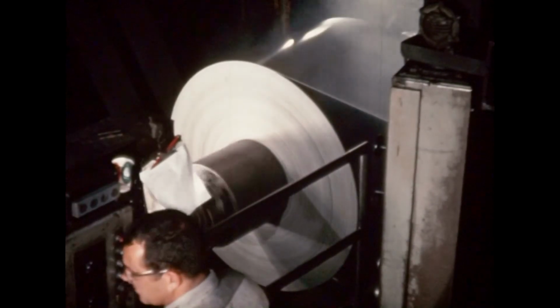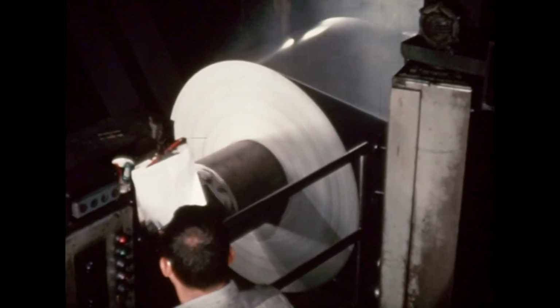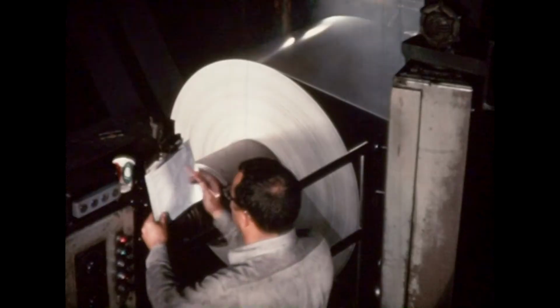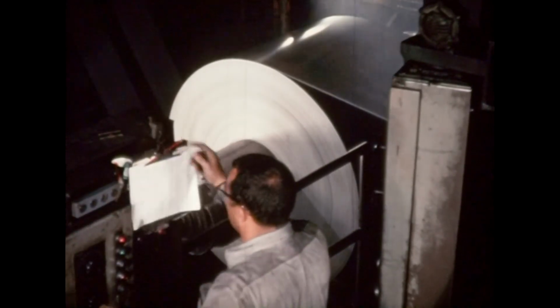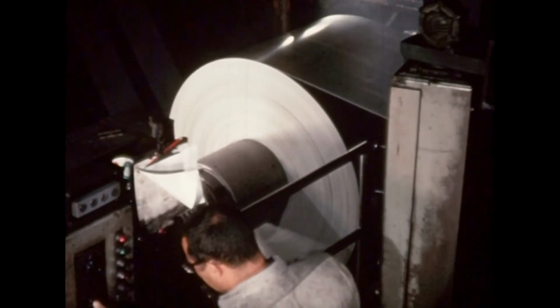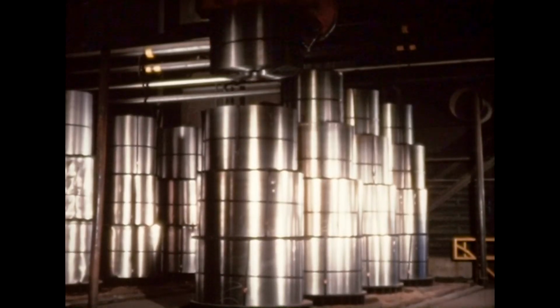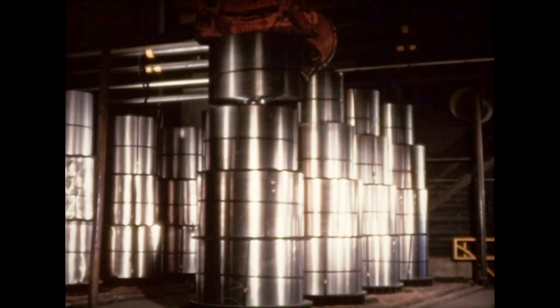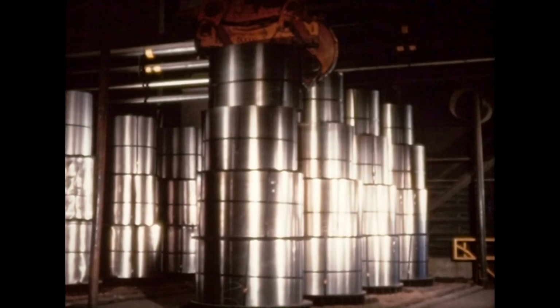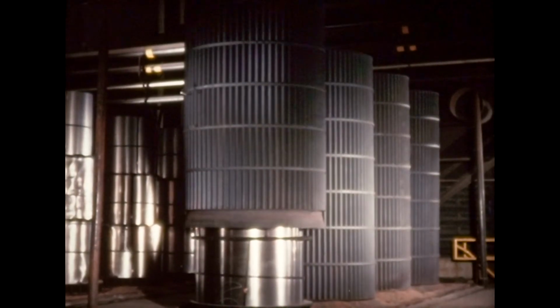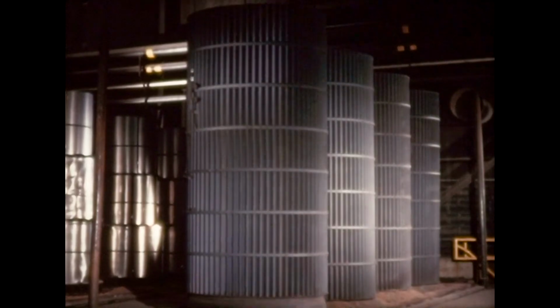Cold rolling hardens the steel, and for most uses, it must be annealed or softened. Now, this can be done by a continuous method or by means of a process called batch annealing, in which coils are stacked and then covered with a portable furnace. An inert gas protects the steel from oxidizing during the process.